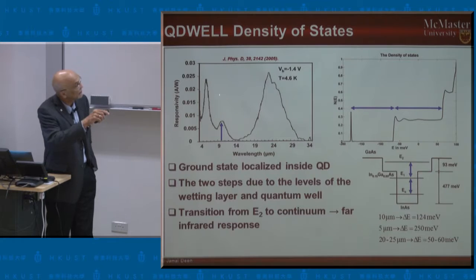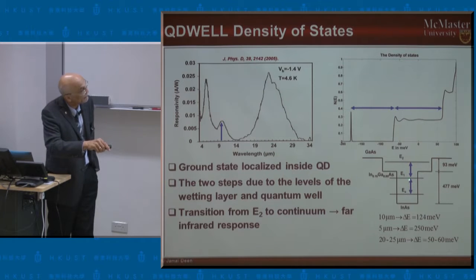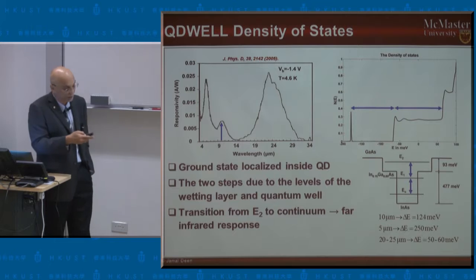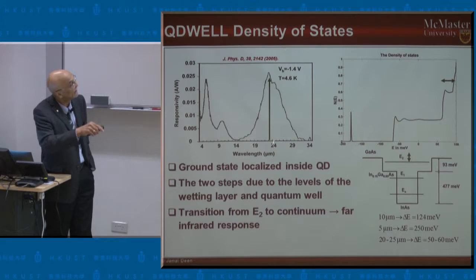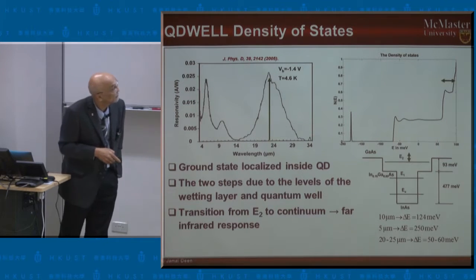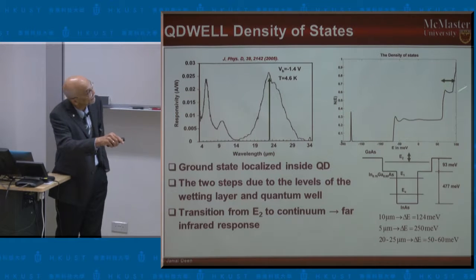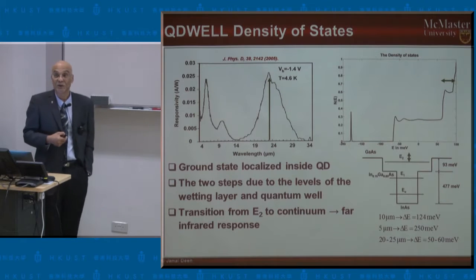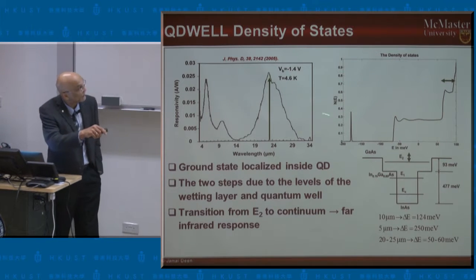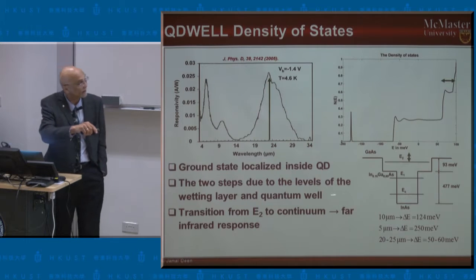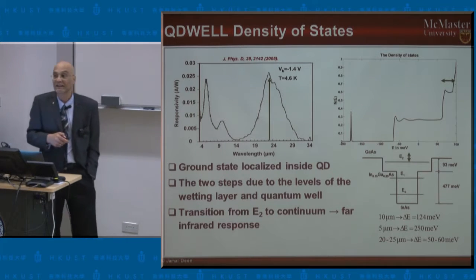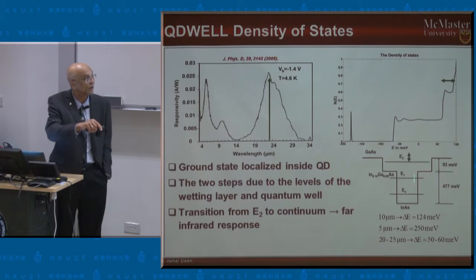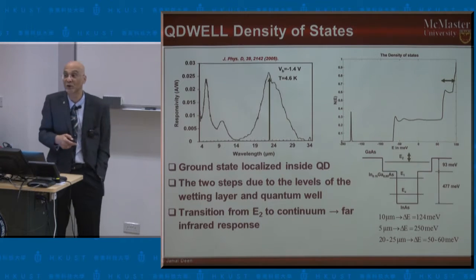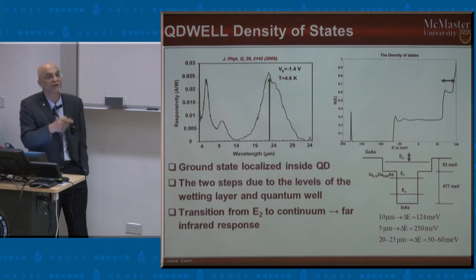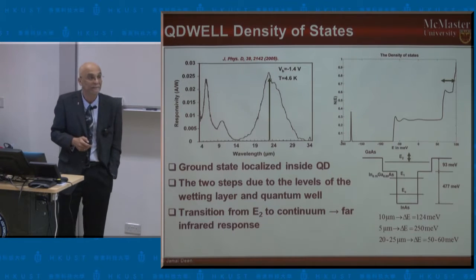This second peak, around 10 microns, could either be from E0 to E1 or E1 to E2. And the third peak that is shown here at around 23 microns is the one that is responsible from here to the continuum. So from E2 to the continuum. So in this way, we can actually look at the structure of the device. We can determine all the localized energy states. And then we can look at transitions between these localized states or from a localized state to the continuum that gives rise to the specific features that we observe in the responsivity.